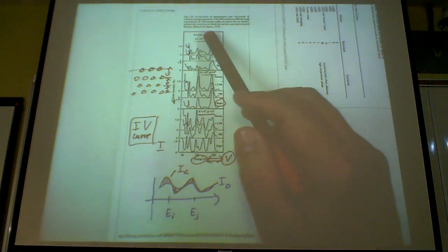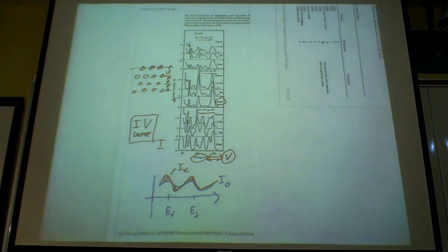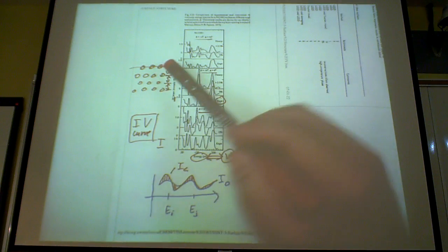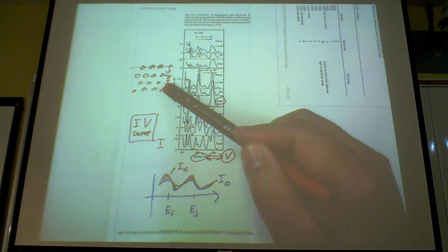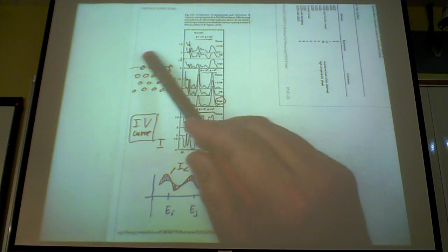So what I do is that I look at my nickel surface and I say, okay, I need a model, right? I then created a model for my nickel 100 surface. And remember, it's not just the top layer, it includes the selvedge, the layer that doesn't have Z periodicity, right? So I created this three-dimensional model.